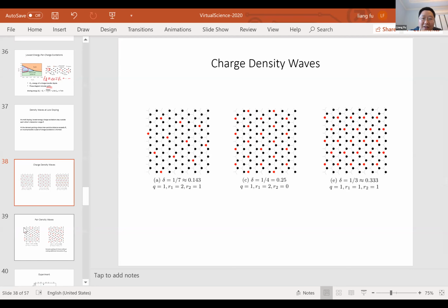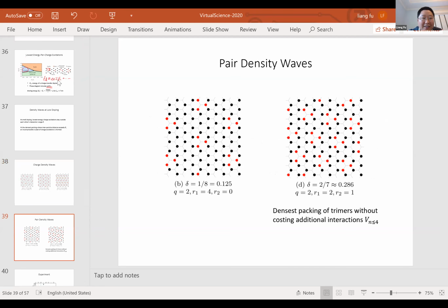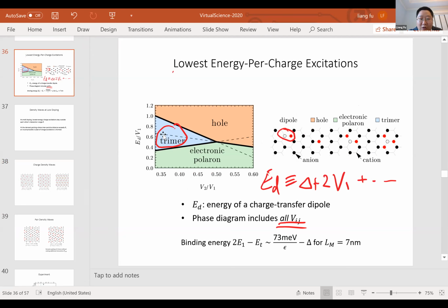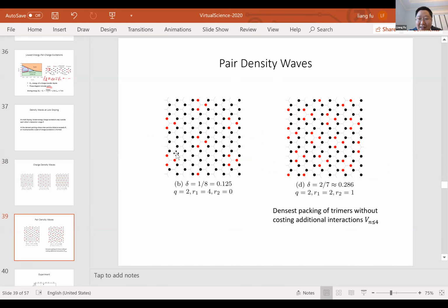On the other hand, remember that there is a parameter range where the lowest energy per charge excitation is the charge 2e trimers. If that's the case, at small doping we can get a density wave of these trimers, which are charge 2e pairs. This is what we call the pair density wave. This is an insulating state of charge 2e pairs in the form of these trimers.